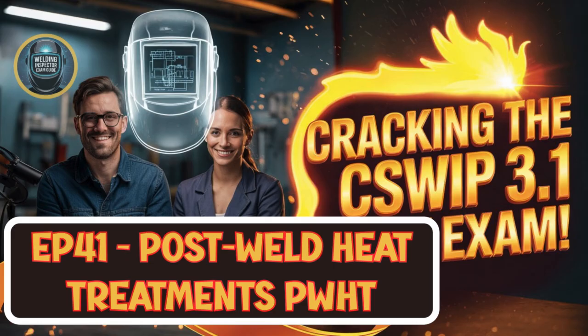Very much so. And just to sort of summarize the keys to effective heat treatment generally, you need adequate support for the part, especially when it's hot and weaker. You need strict control over those heating and cooling rates. You need that sufficient soak time for the whole thickness. Avoid direct flame impingement. Sometimes you even need to control the furnace atmosphere to prevent excessive scaling on the steel. It's a whole package of careful control.